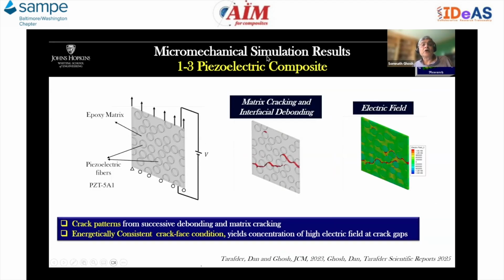So here is a model of micromechanical simulations for a 1-3 piezoelectric composite. Here you have an epoxy matrix and piezoelectric fibers, PZT5A. Here we are applying both a mechanical load as well as an electrical load. And here you see the evolution of the matrix cracking together with interfacial debonding in the microstructure. Because of the energetically consistent crack face condition, you also see this localization of the electric field in the microstructure. The crack patterns from successive debonding and matrix cracking are shown here.